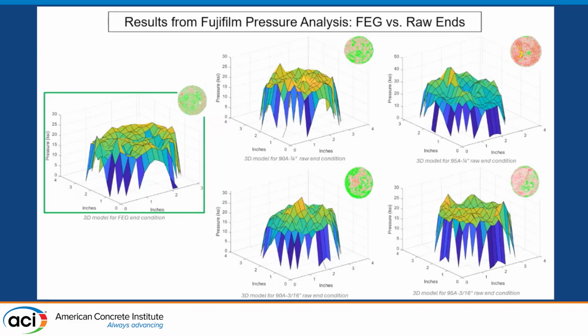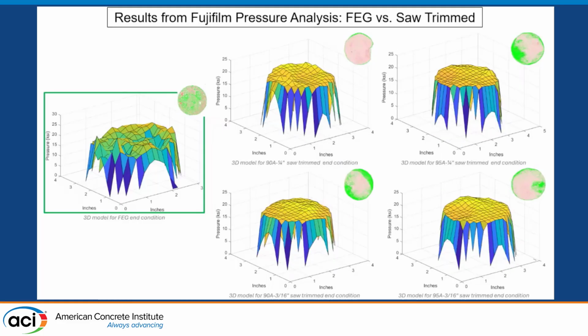What I'd like to note here is that the raw end shows a lot of variability across the surface, as expected. I mean, we didn't do anything to these end conditions. We just put them in there, put the cap on, and let them cure. But interestingly, in the same batch, the saw trim cylinders showed a more uniform distribution, which showed us that the ends were able to be smoothed out. And the fixed and grinded condition, although it's still variable, we're still able to produce similar results in this case.